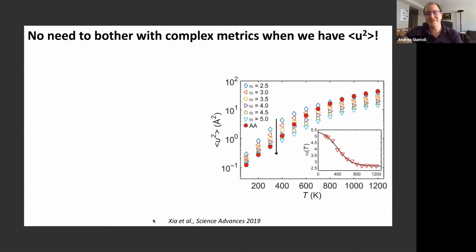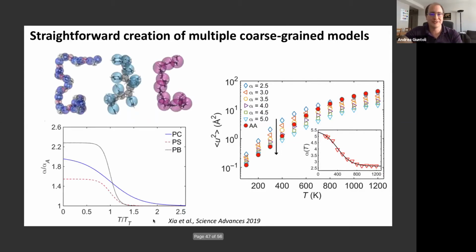So the only thing you need to do is actually to have your Debye-Waller factor with temperature for your atomistic system and tune the Debye-Waller factor of the coarse-grained system as well. And just by doing that, it's straightforward to create this parameterization, and they created it for a lot of different polymers, for example, polycarbonate, polystyrene, polybutadiene. And these are models that we are now using for our simulations that are coarse-grained, but still chemistry specific, which is a huge advancement.